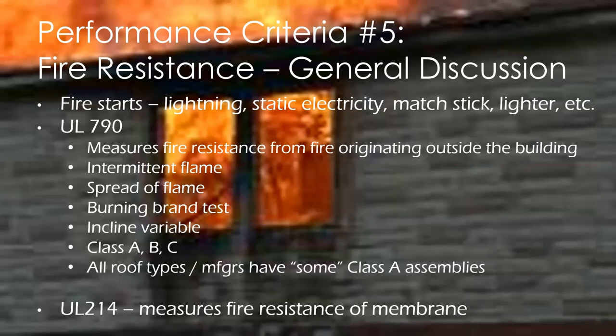One would be the spread of flame, the intermittent flame, and the burning brand test to give you that A, B, or C rating. When we look at spread of flame, what it basically does is it spreads the flame across the surface of the assembly and holds it there for 10 minutes. Based on that spread, you get a Class A rating if the spread does not exceed 6 feet. A Class B will be a roof flame spread that does not exceed 8 feet. And this is the only test method required for metal, concrete, or poured gypsum decks: the spread of flame.